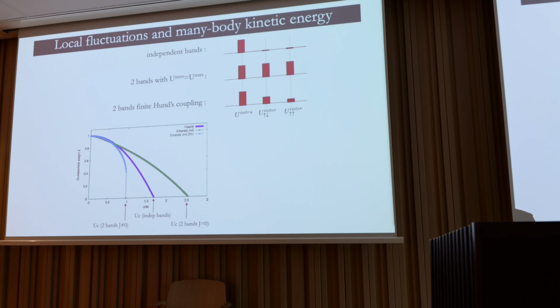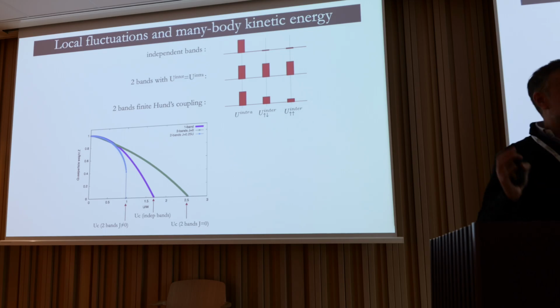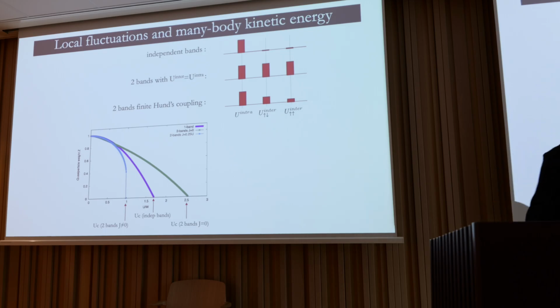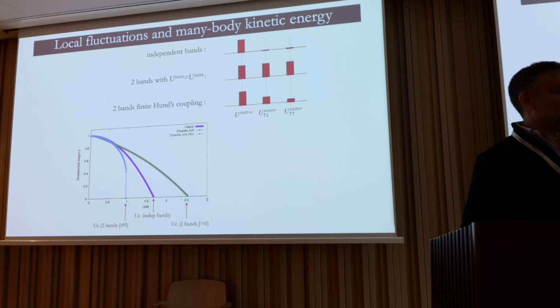Question: is it a Mott transition or a selective Mott transition? It's a true Mott transition, because the bands are identical. This simply tells you that you cannot simply view this as a competition between band delocalization and interaction strength—it's more complicated than that. And the complication is exactly what Hund's coupling exploits to make a more correlated compound.